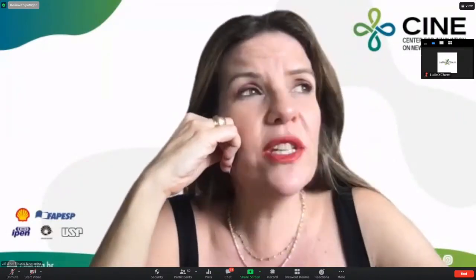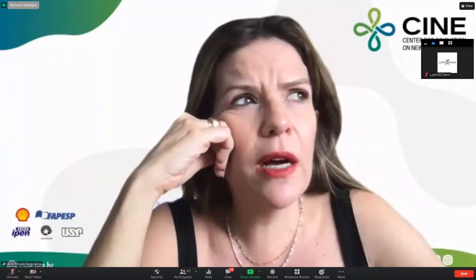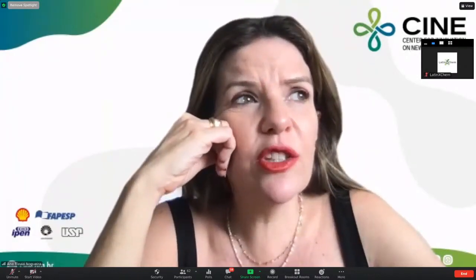Okay, so we're just planning to do that just before the turn off of the UVX. We have a proposal now in Berkeley, where we're expecting to look at the effects of temperature on the stability of these perovskite films. We did a work with Giulia Grancini last year, not in FAPI, but in 3D/2D, because a lot of work now involves 3D perovskite with a layer of 2D. Also using the synchrotron, we showed that when you heat up these 2D/3D interfaces, these 2D phases totally disappear.